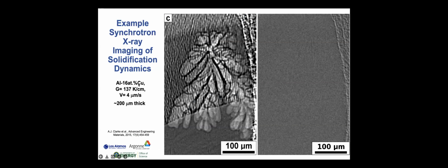So this is an aluminum copper alloy, and here we're controlling processing parameters. We're controlling G, the thermal gradient, and V, the solid liquid interface velocity. And this is for a 200 micron thick sample. And just for context, a human hair is on the order of about 100 microns in diameter. So we're talking about the thickness of 2 human hairs.